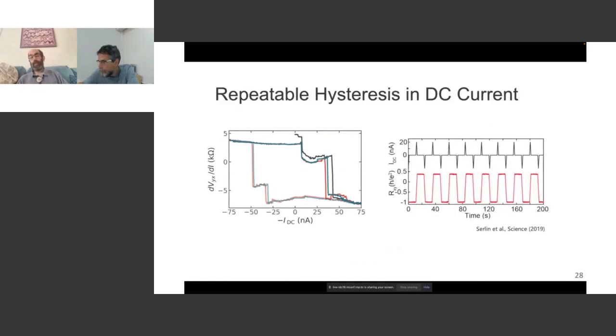We found, and Andrea's group verified, something that was also surprising, that we didn't need to switch the magnet with a magnetic field. We could actually switch it by driving a current in the plane, a very tiny current. And so you can see we can go around this loop reproducibly and switch the magnetic state as read out by the Hall effect. They showed this similarly. And this is really pretty striking, because being able to switch a magnet electrically is attractive for storing information in memory in a computer.